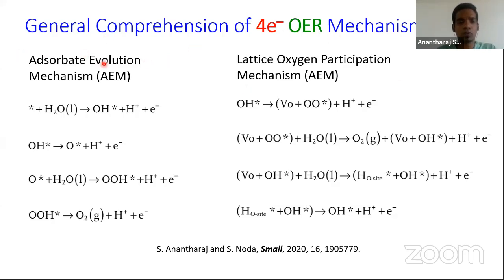I mean, adsorbate evolution mechanism or lattice oxygen participation mechanism. In adsorbate evolution mechanism, the oxygen which is evolved at the end of the reaction is not at all coming from the catalyst lattice, because we know in OER, whatever the material that you use, the real-time catalyst is always going to be the oxyhydroxide that is formed electrochemically on the surface, which means that the catalyst, which contains oxyhydroxide, which contains oxygen, can participate in the evolved oxygen. I mean, the oxygen which is evolved because of the water oxidation reaction may also contain oxygen from the catalyst